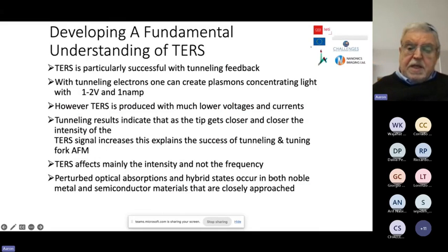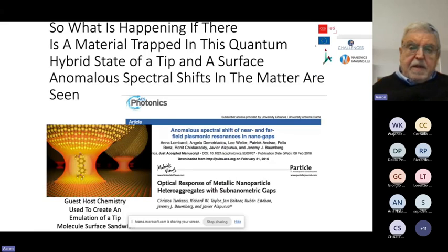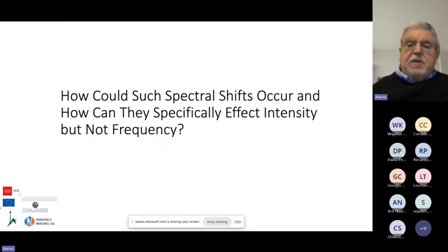So perturbed optical absorption and hybrid states occur in both noble metal and semiconductor materials that are closely approached with the tip, okay? So what we see over here is that you get a hybrid state. The hybrid state is like a new molecule because the distances we're talking about are angstroms. And if you even look at a hydrogen-hydrogen molecule, the hydrogen bond is 0.5 angstroms, okay? So we're talking about angstroms generally in molecules, and we know that chemistry is based upon changing the electronic nature of molecules. So how could such spectral shifts occur, and how can they specifically affect intensity but not frequency?